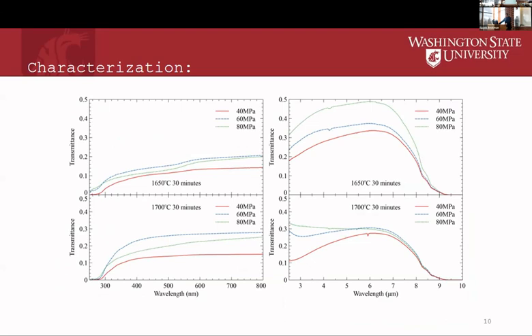There's an important reason for that: during the sintering process, the graphite pulls oxygen off of the yttrium oxide, and you form oxygen vacancies, which are color centers in the material. These are more absorbing in the visible region, and that degrades your optical properties there. The other primary thing is porosity, which in the IR region is the primary limiting factor for our transmittance measurements.